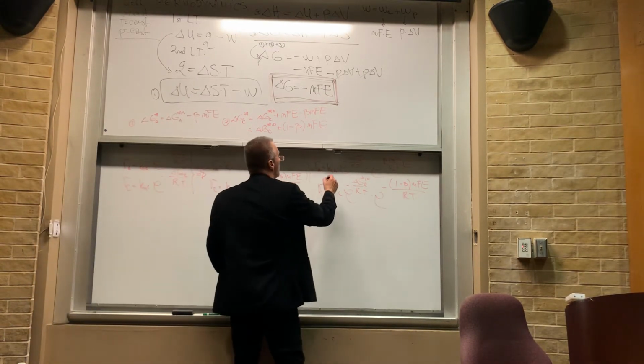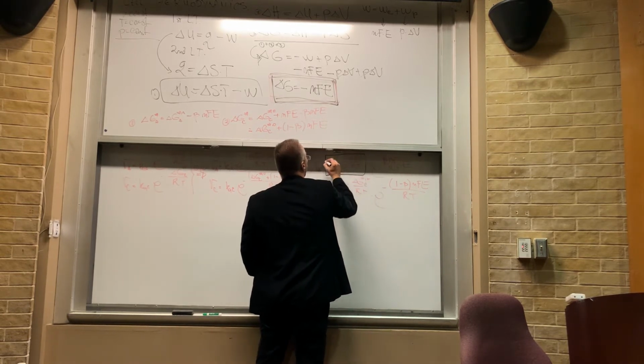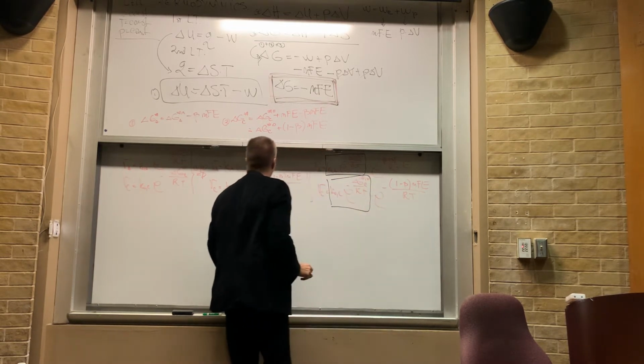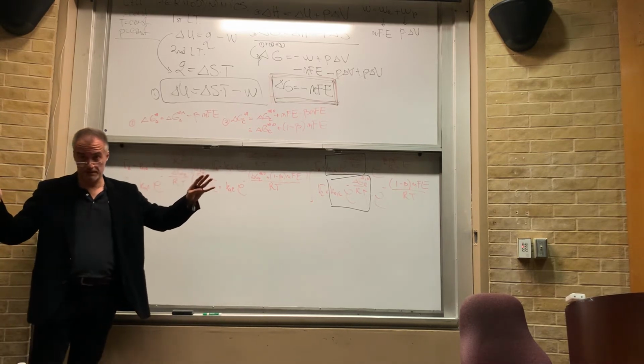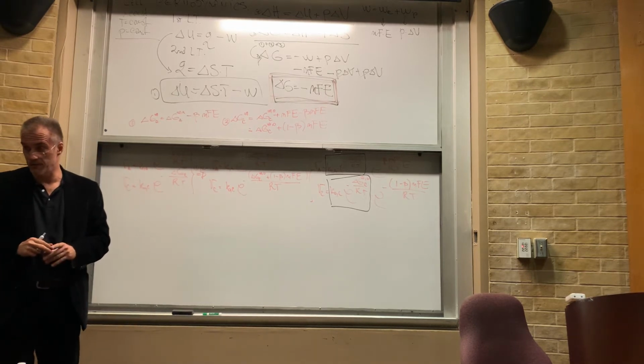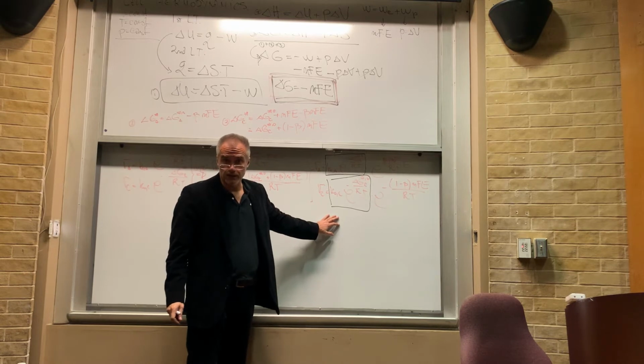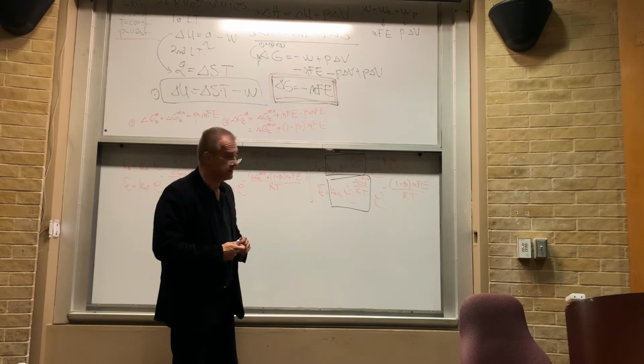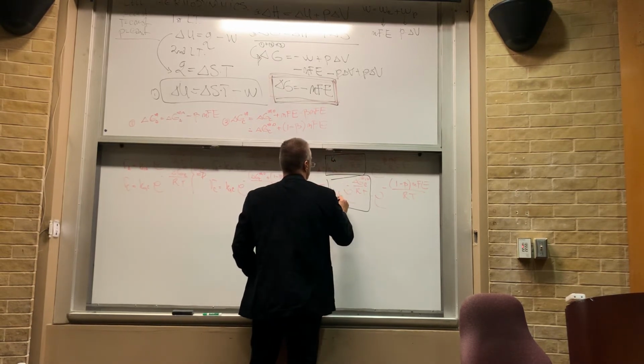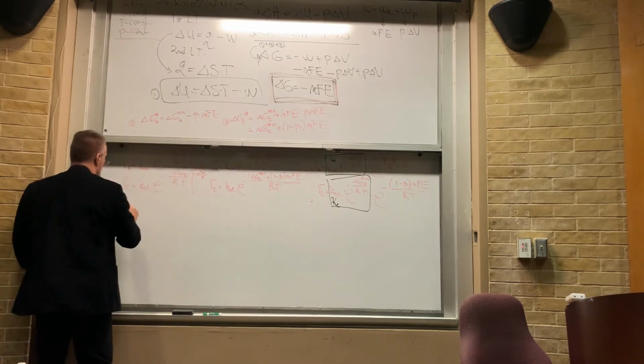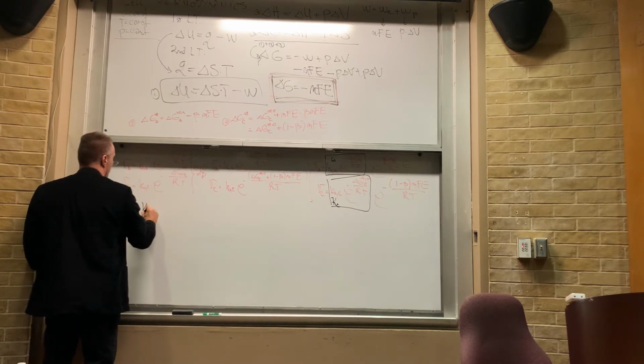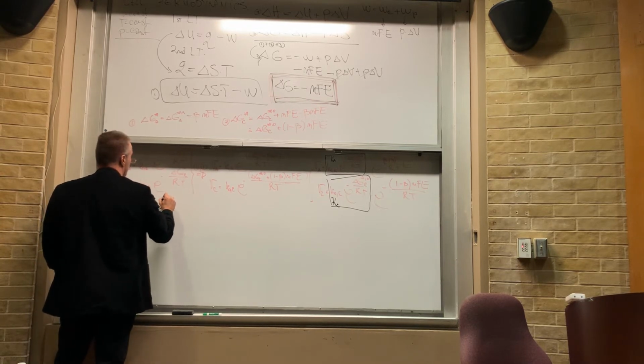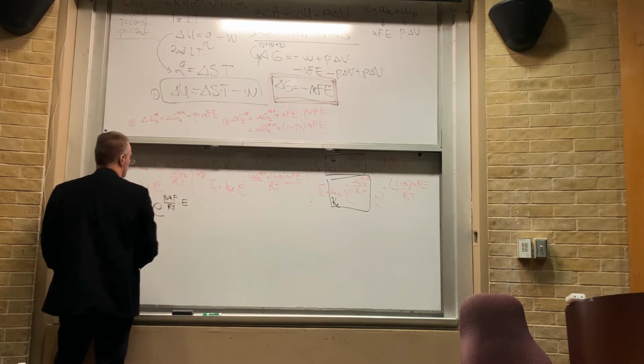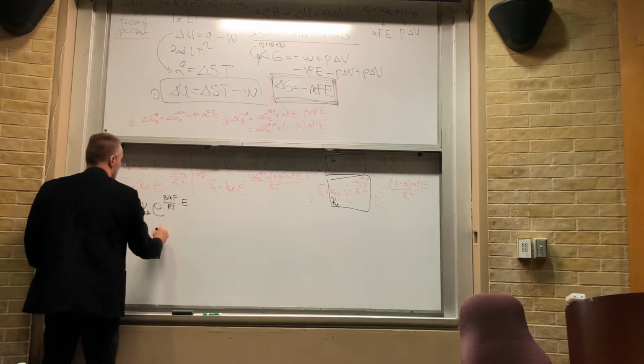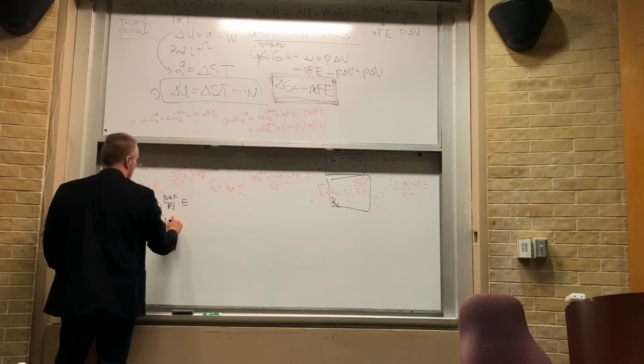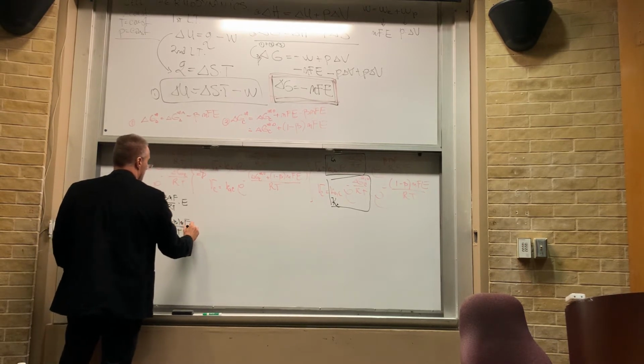But here's the cool thing. This part here and this part here are something that we know where it comes from. Those are just this chemical affinity. Remember, those are the black curves in our diagram, right? So these are actually our chemical rate constants, which we defined, if you remember, I discussed that. So this here is the K_A, and this here is the K_C. So finally I can write the rate of the anodic reaction to be equal to K_A e to the βnF over RT times E, which is the potential across the interface, and R_C is equal to capital K_C e to the minus (1 minus β)nF over RT times E.